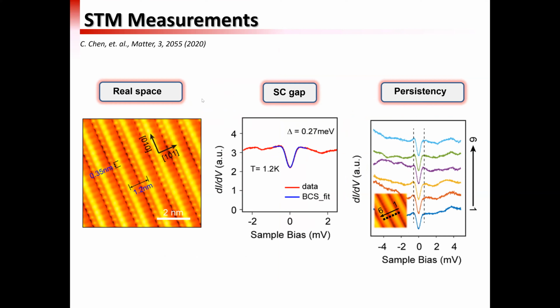we also use STM measurements. This shows the 1D tantalum triselenide chains. You can see clearly that the superconducting gap opens when the temperature drops below the transition, which is around 1.75 Kelvin. Very interestingly, even if we vary the STM tip position across the wires, as you can see in this inset, from one chain to the other, we sampled six points and measured the STS spectra, and they show quite similar behavior, so it's homogeneous on the surface.